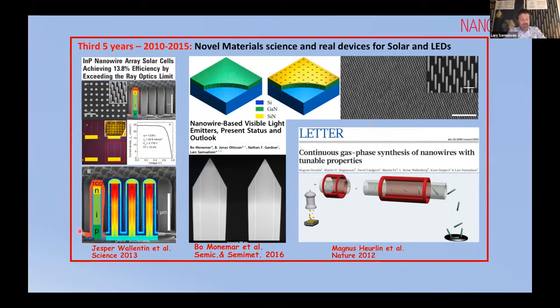The stuff that Jesper Wallentin and Magnus Borgström developed for indium phosphide nanowire array solar cells, achieving 13.8% efficiency by exceeding the ray optics limit, where you see the very careful design of the spacing, the internal structures, diameters, lengths, contact regions, and everything to optimally absorb the light. Even when we only covered, say, 10 or 12% of the surface with nanowires, we could absorb, if not 100%, at least pretty close to 100% of all the photons.